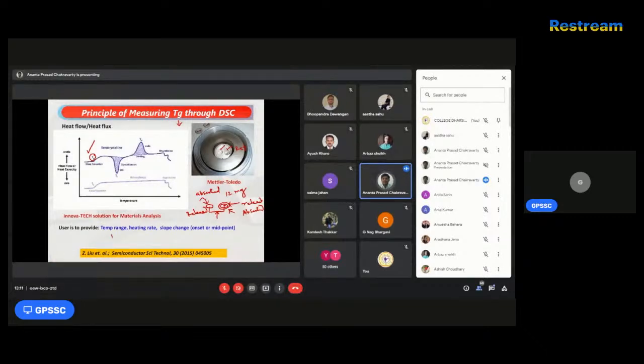Generally this test requires you to provide data, like at what temperature range you want to scan, then the heating rate, that is, the change in temperature with respect to time, then the slope change. That means whether you want the onset value at the slope or the midpoint at the slope, that is also required.